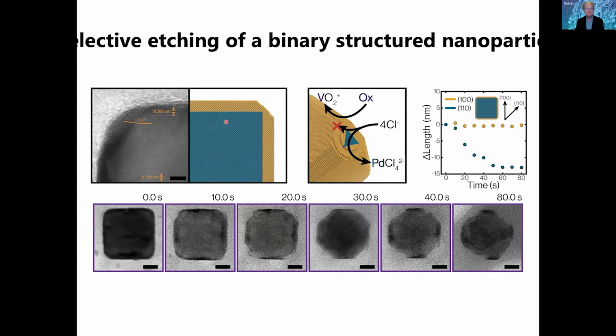And here you see an example where we have taken a particle that has both platinum and palladium and gold components to it. It's a particle that has this kind of core-shell-like structure. And we are able to selectively go in and etch away one of the components while leaving the other one completely intact. So that's just a demonstration of the ability of controlling this local redox potential.